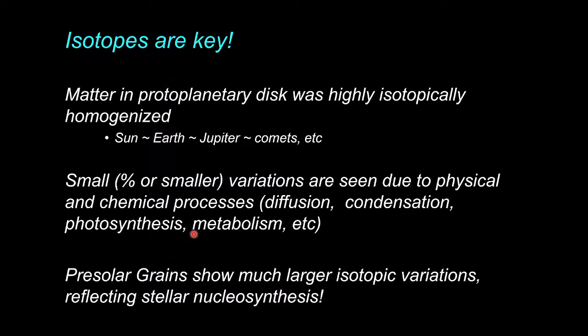And the reason is that when the protoplanetary disk formed, it was very hot, and even in the molecular cloud before, a lot of the material that existed before got homogenized. And in the disk, most of the pre-existing dust got evaporated and recondensed, and everything got isotopically homogenized. And that means that the isotopic composition of the sun, the Earth, Jupiter, and comets are all pretty similar. There are very important differences that tell us a lot about the formation of the planets and the sun, but they're much smaller variations, on the order of percent variations. There are all kinds of physical and chemical processes that can cause percent level or less than percent level changes in isotopic composition.